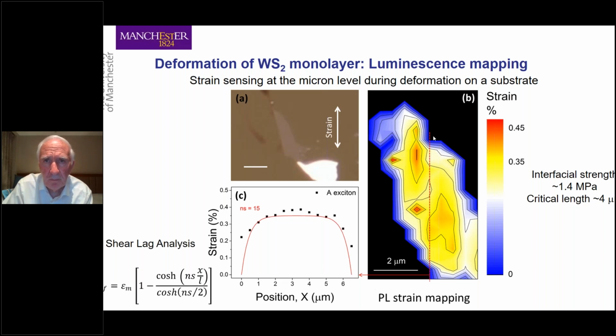edges. If you measure the strain along the line as shown over here, you get these data points from individual measurements, and you can actually map out the strain distribution theoretically using standard shear lag theory, which people use in composites. So this is for a single flake, but I think it's fairly easy to see a situation where you could have lots of flakes inside some sort of paint type structure, and you could actually use that for measuring strain with quite a high degree of precision.